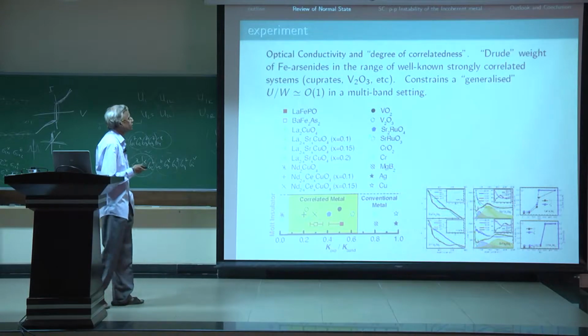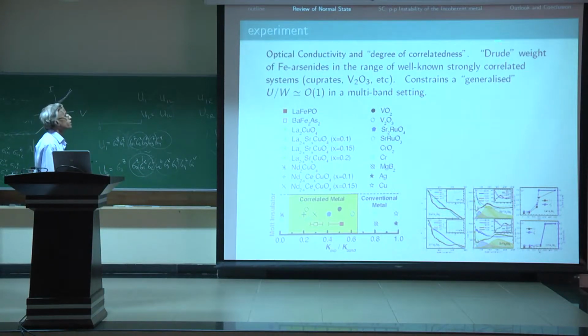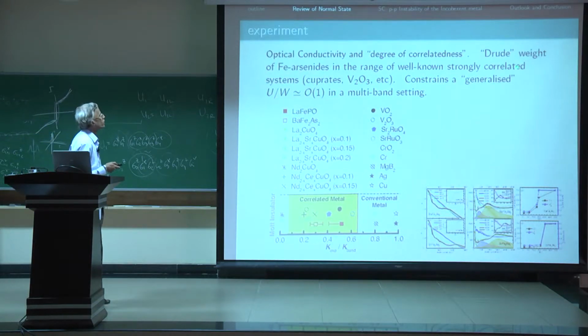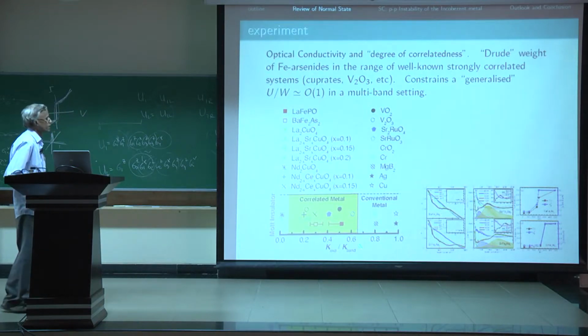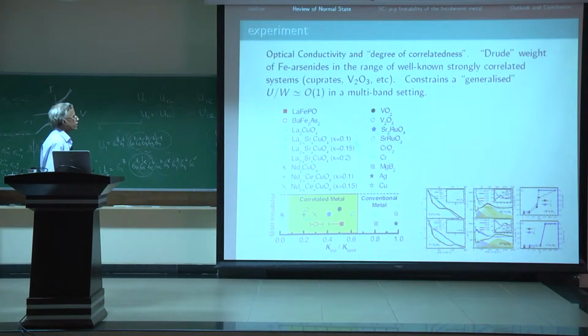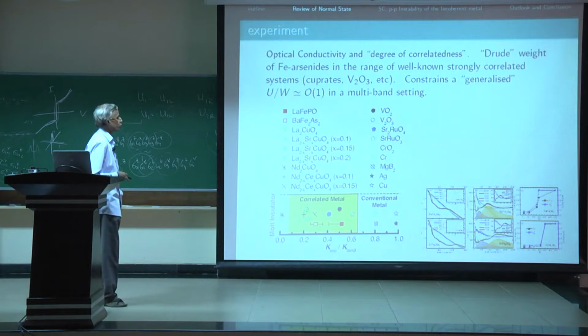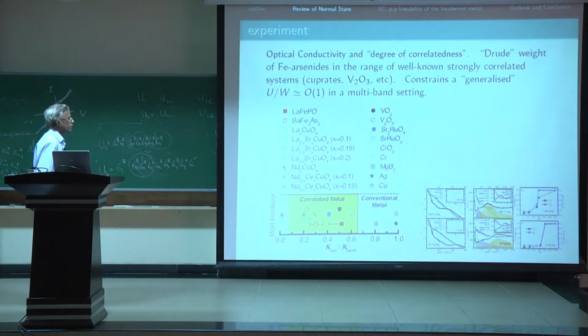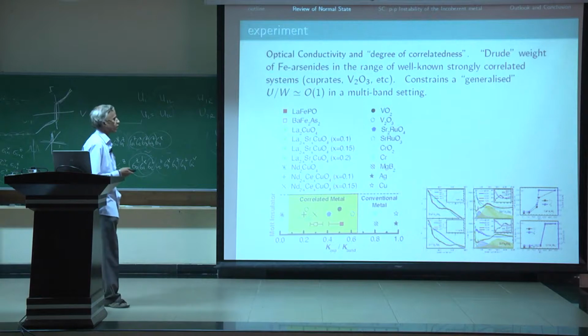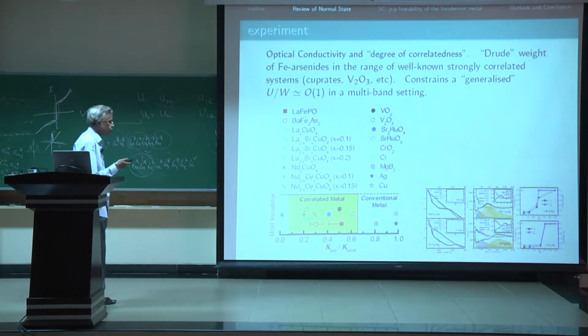by Basov and co-workers in the early days of iron pnictides, where they looked at the degree of correlatedness, which is the weight of the Drude low frequency component in the optical conductivity relative to the band structure value evaluated from DFT. And you can see that the iron arsenides lie in a region which is associated with correlated metallicity. In fact, they lie close to the doped cuprates, in contrast to very good metals where this ratio is almost 1. Here it can be decreased to 0.2 of the band structure value. So that would seem to suggest that one should treat these as strongly correlated materials.